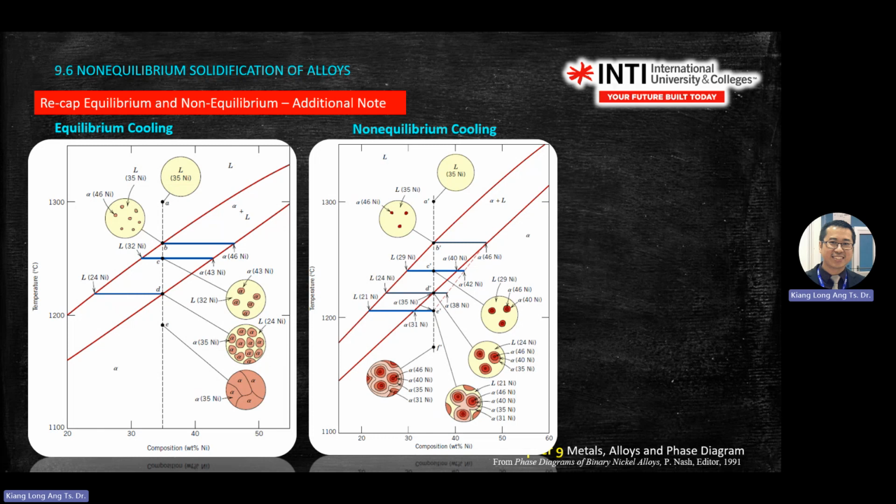Okay. The rapid cooling one will have a join of the previous one. It will have another layer. It will carry forward the previous one, but the normal cooling one doesn't have that. You see the left and right? You see this one got 2 layers. So the inside one has the previous one, 46%, and then the outside one has 40% here.